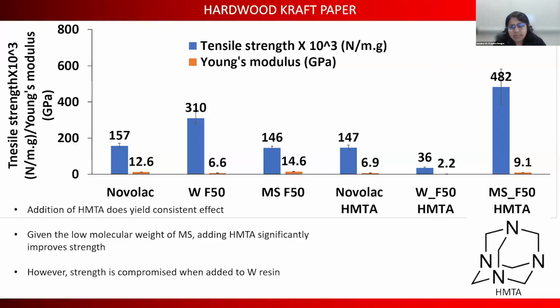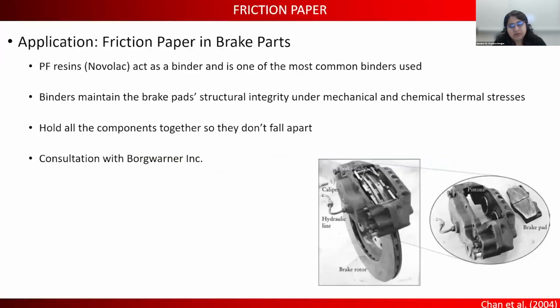Once we had tested our resins on the hardwood kraft paper, although this was only one layer of paper, we were not able to test multiple layers of paper for this application to truly determine the performance in a real setting. So this was more just to show that the resin did work well even with kraft paper, where you would expect some interaction between the paper and the resin, which was not the case for the glass fiber and the resin. So then we looked into a second application.